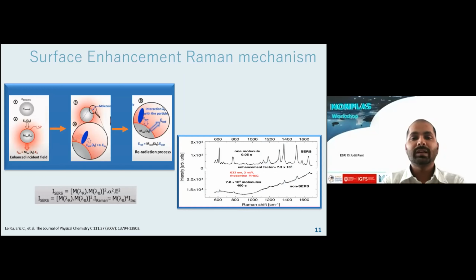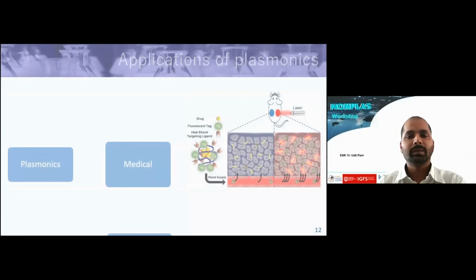There are two kinds of enhancement, but the dominant one is electromagnetic enhancement, which helps to enhance the signal from 10 to the power 6 up to 10 to the power 10, 12, 14 times. And it is because of the plasmonics.